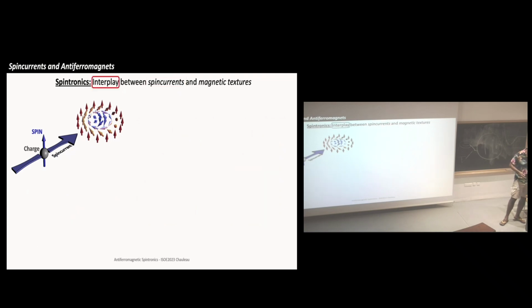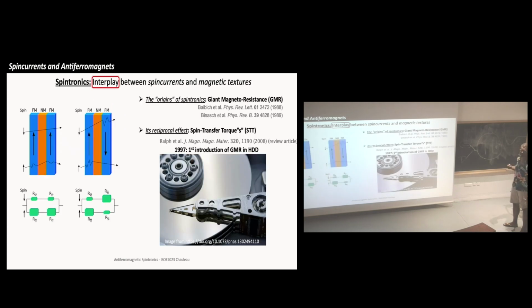Then the second concept, of course, is the interplay. And the easiest way of seeing the interplay is looking at the origin of spintronics, and Michel has already introduced this quite a lot, so I will go quickly. It is, for example, the concept of giant magnetoresistance, where the magnetic texture plays a role on the electrical conduction, and vice versa, the electrical conduction can play a role on the magnetic texture by switching through spin torque. So that's really the interplay between magnetic textures and spin polarized current.